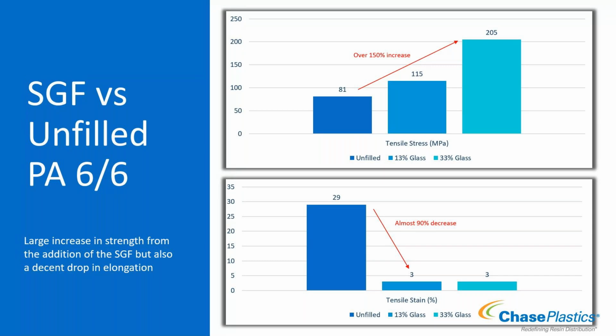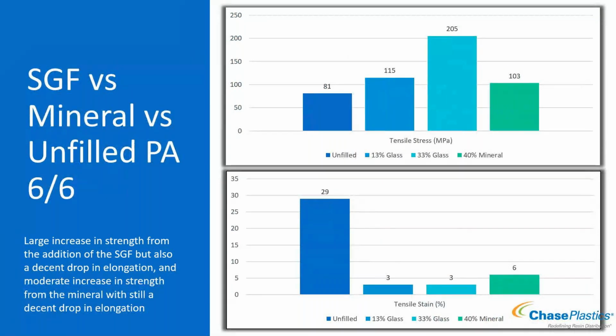As we mentioned, mineral also sees an increase in stiffness and strength and a decrease in elongation. So now more data to show that - same materials, but now with addition of 40% mineral 6.6. Going from 81 MPa unfilled, it jumps to 103 - an increase, but not as dramatic as with glass. And 29% elongation drops down to 6% when you use mineral. So increased stiffness and strength, lower impact and elongation.